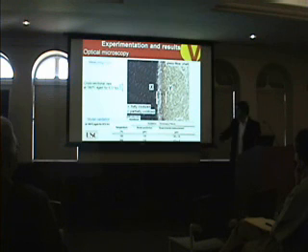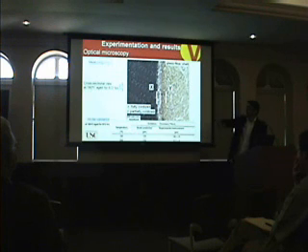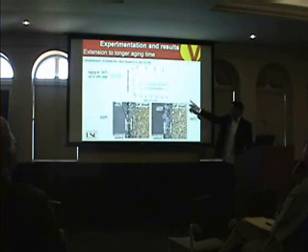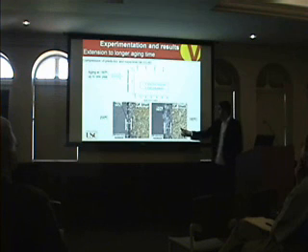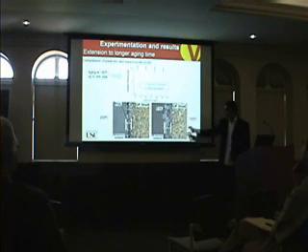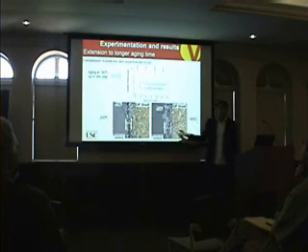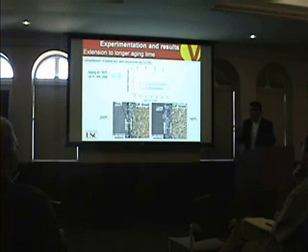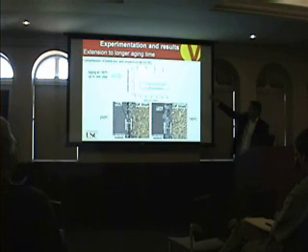And this is the comparison of the modeling and also the experimental results after 4 weeks at 180 degrees C. And as you see, those are so close. So we extended our model up to 52 weeks. And this is at 180, and this is at 200 degrees C. You see that the oxidation thicknesses are almost the same, and they didn't change. And that's the prediction, and that's the model.